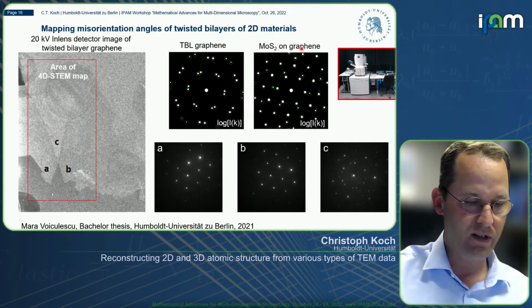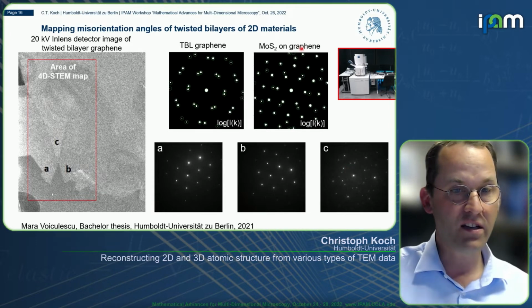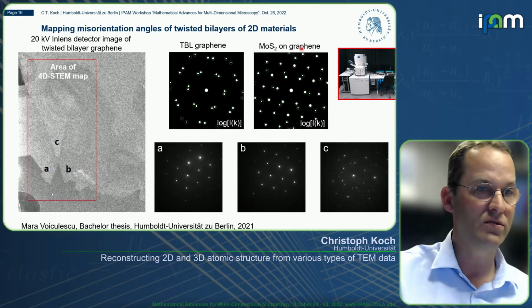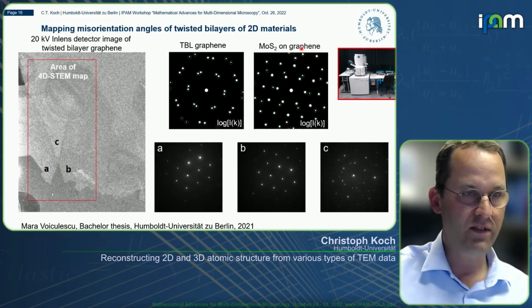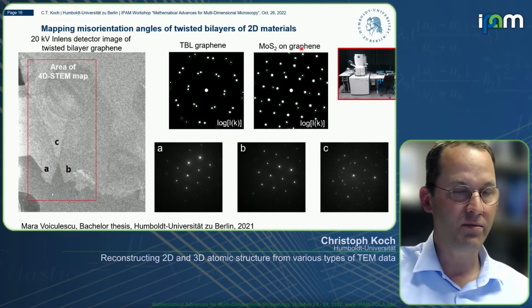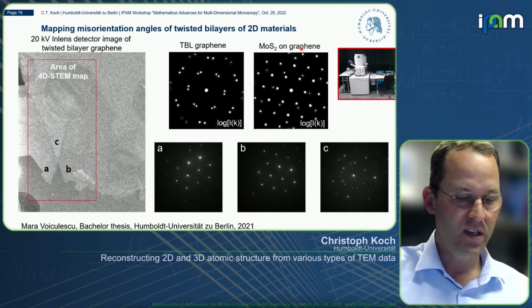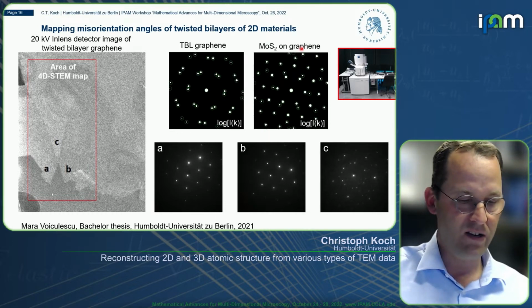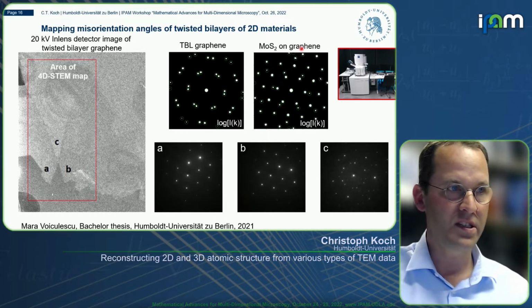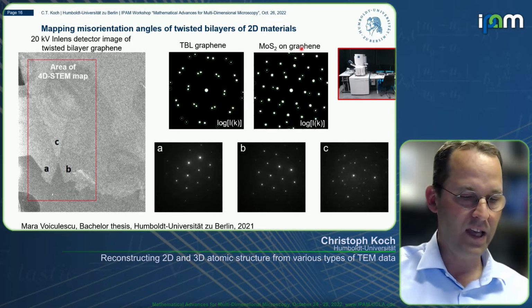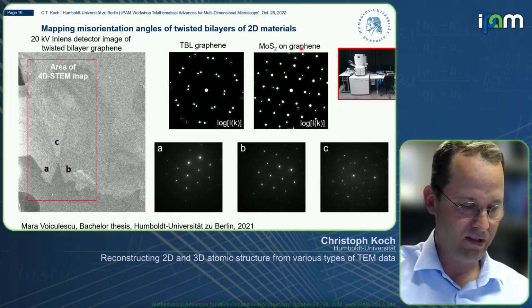of 2D materials. And you can really characterize these without having to go to a TEM and without having to spend very high dose on your sample, which reduces also, of course, the damage and allows you to really plan your experiment for the TEM without having damaged it too much beforehand.